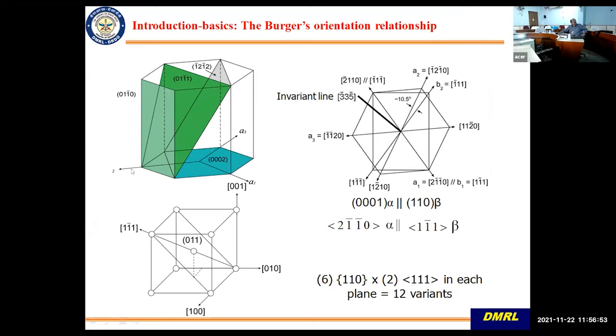Here also I'm showing both the structures, and whenever you transform beta to alpha, that is, you cool down after heating to beta phase, there is a Burgers orientation relationship which is followed. That is, the close packed plane of this matches onto the close packed plane of this. That is what is shown here, the hexagonal basal close packed plane, and this plane, which is this. And you can see there is only one direction in which it matches perfectly. Other direction, there is a slight mismatch.